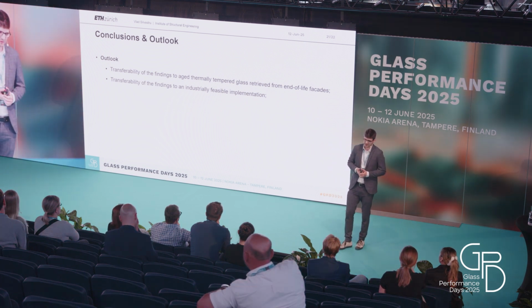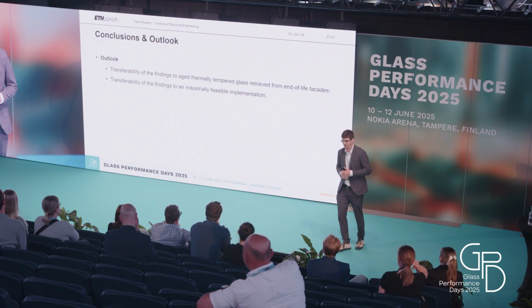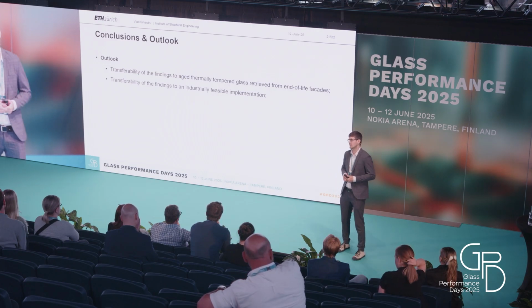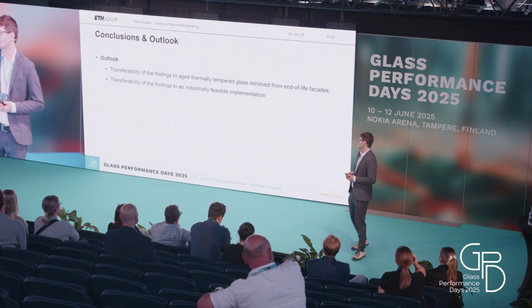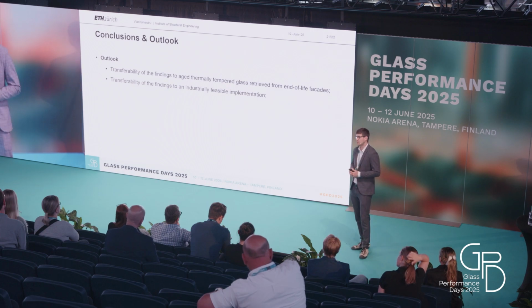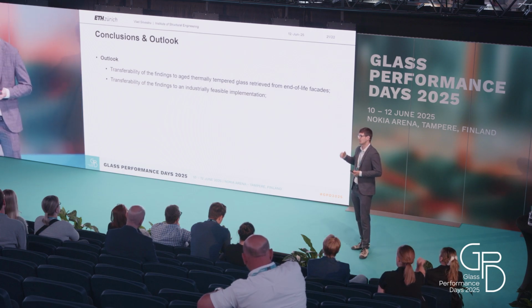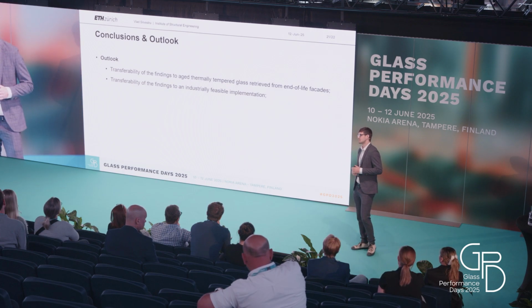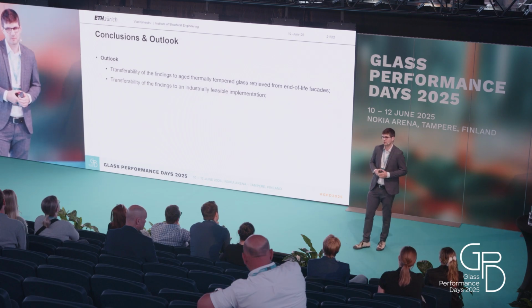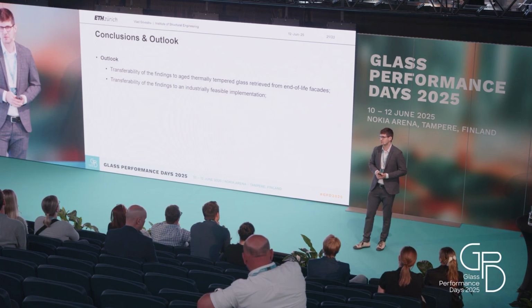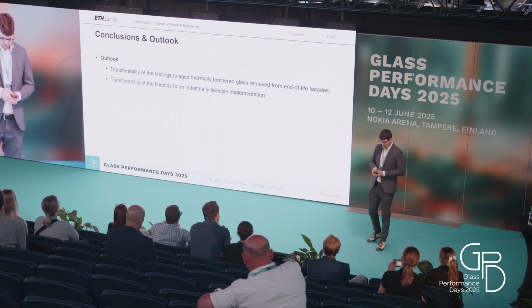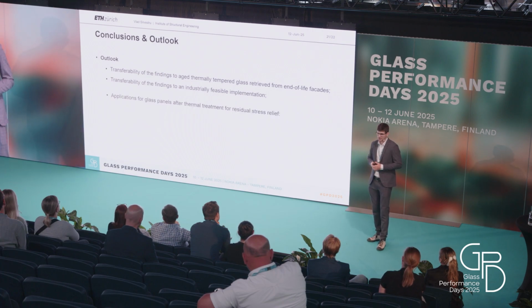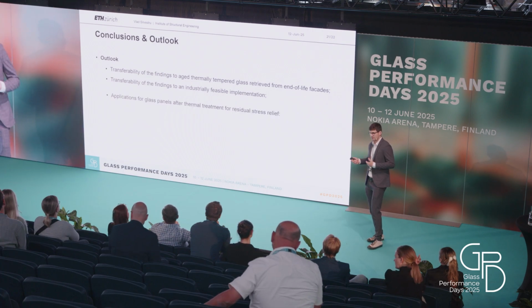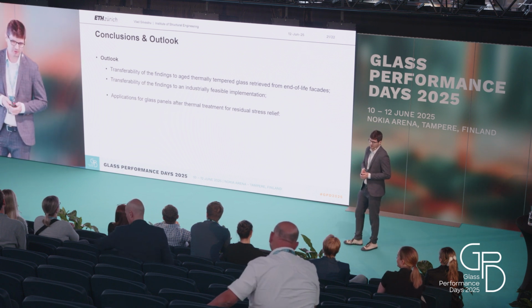And then also the transferability of the findings to an industrially feasible implementation. I think the main challenge is the required cooling time. So it needs to be cooled relatively slowly. And for industry, this might be only interesting if there is enough amount of glass to be processed like this. And also the application of the glass panels after this residual stress relief treatment.